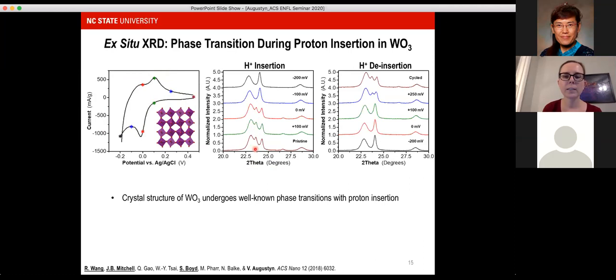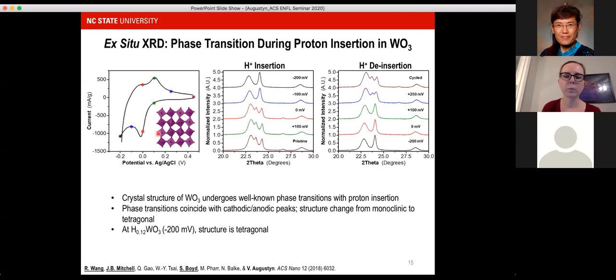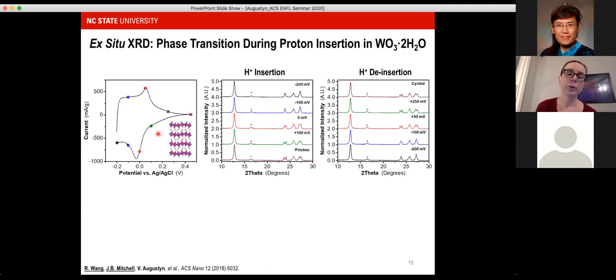And we see there's a discrete phase transition that takes place right around this region here that's associated with the redox peak. The structure goes from monoclinic to tetragonal, and that's as we expected. What we didn't expect is what we observed for the hydrated tungsten oxide. This is a cyclic voltammogram of one of the larger, platelet-like materials that I showed at the beginning. We used those materials for the structural studies because we wanted to have very crystalline materials.